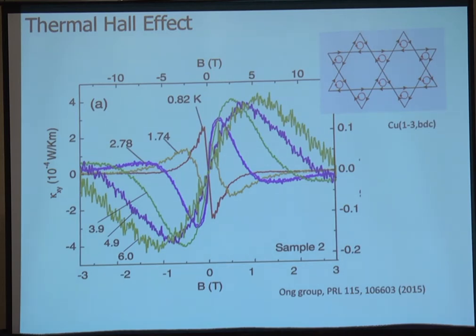The topological charge is related to the topological Hall effect. And Charles asked whether there is a topological Hall effect for this model. The answer is yes and no. Model-wise, theoretical-wise, it is true. But in reality, our B20 compound is an itinerant magnet. This is a Monte Carlo calculation. It's based on the assumption that the local spin is persistent from low temperature to high temperatures. But for itinerant magnetism, at high temperatures, there will be no local magnetizations. So that's why there will be no such additional topological charge outside the skyrmion phase.